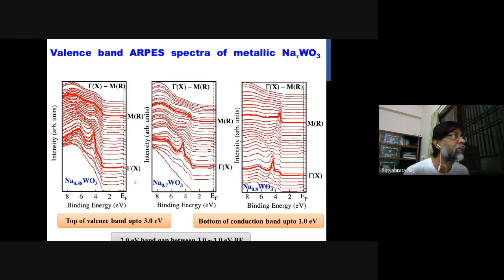And this gives 0.58, 0.7 and 0.8. You can see that gamma is the center of the Brillouin zone, and M is the extreme point of the Brillouin zone. A very simple band structure says that the valence band is up to 3 electron volts, and the conduction band lies up to 1.0 electron volt, and there is a 2 eV complete band gap for any doping. That gives the high band gap of WO3.